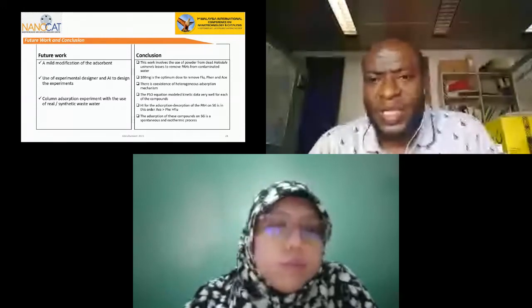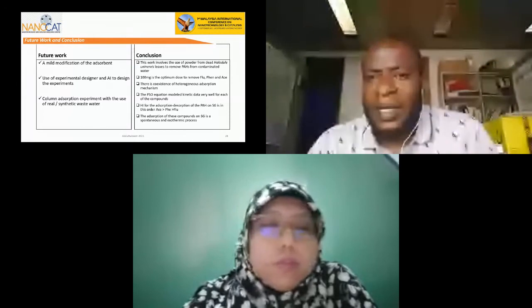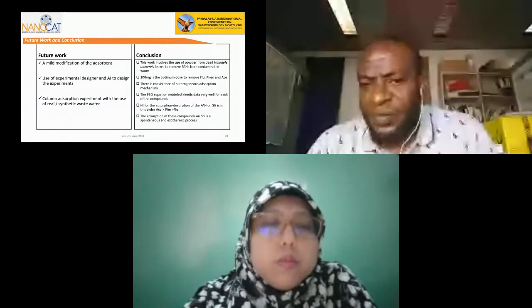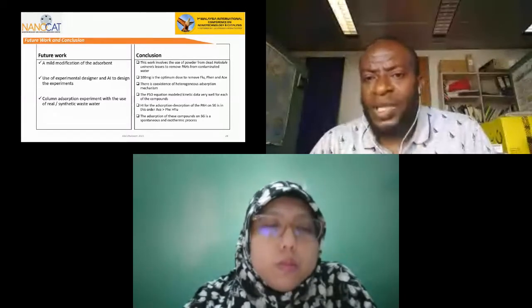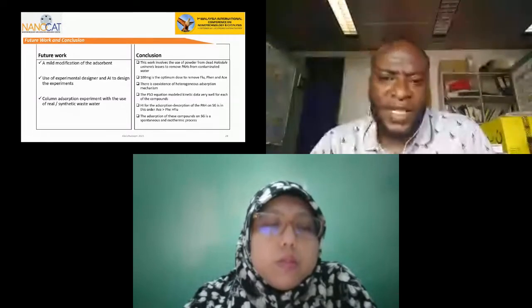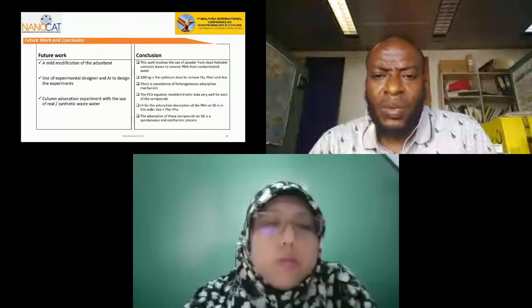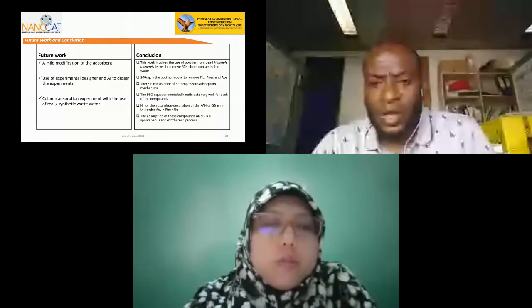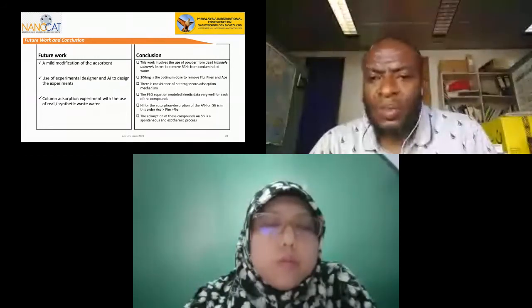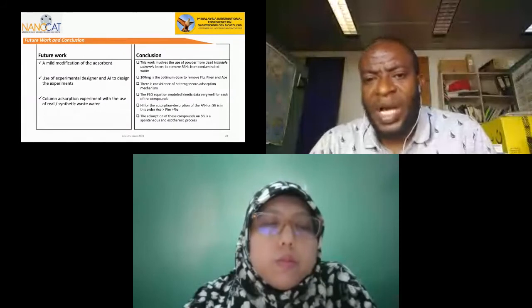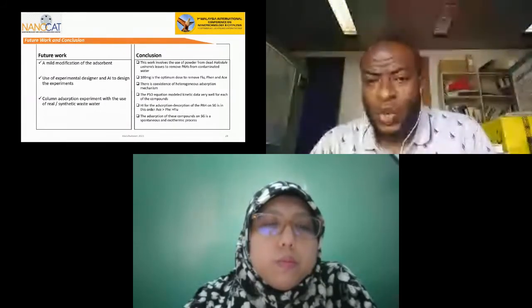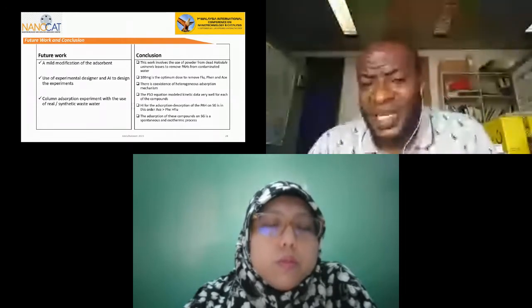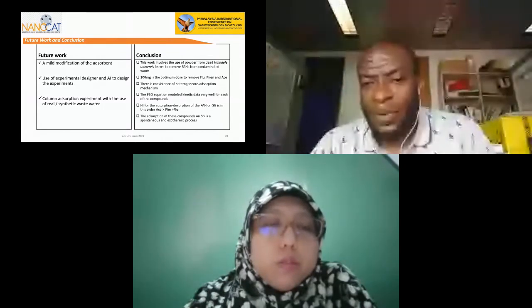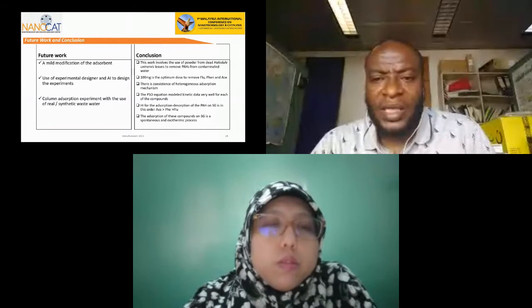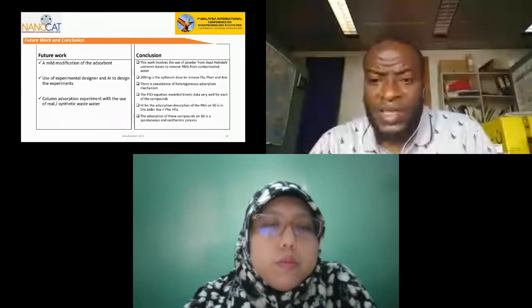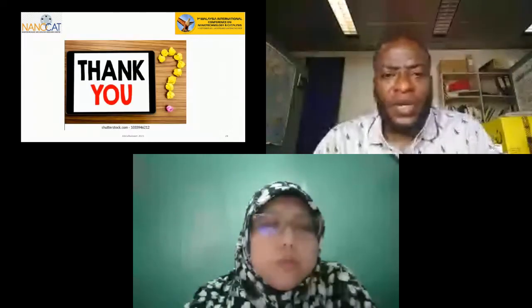Conclusion from this work is we do know that this particular powder from the dead Halodule uninervis leaves can remove PAHs from contaminated water, and 100 milligram happens to be the optimum dose to remove fluoranthene, phenanthrene, and naphthalene. And we suspected that there is coexistence of heterogeneous adsorption mechanisms. The second order kinetic model fitted the kinetic data very well for each of the compounds. And the thermodynamic index showed that the strongest attraction existed between fluoranthene and the adsorbent, followed by phenanthrene, then followed by naphthalene. And the adsorption of these compounds on seagrass is spontaneous and exothermic. Thank you for having me, and for your questions.